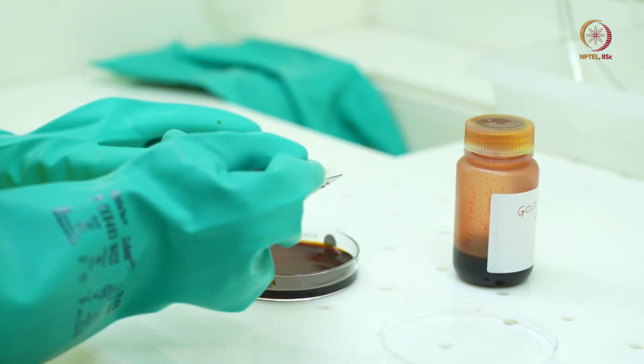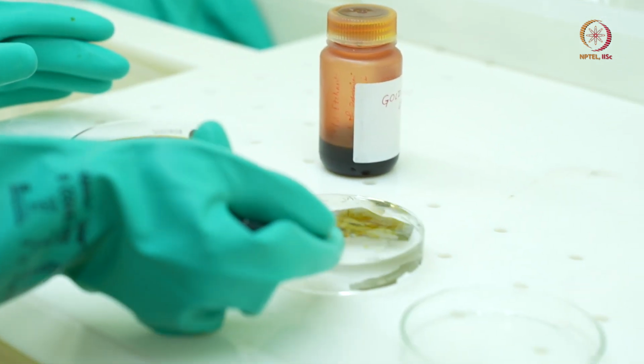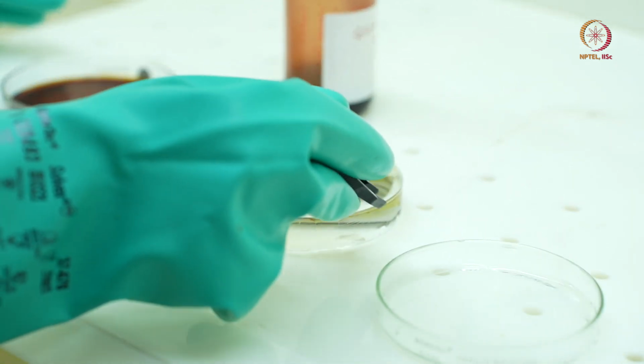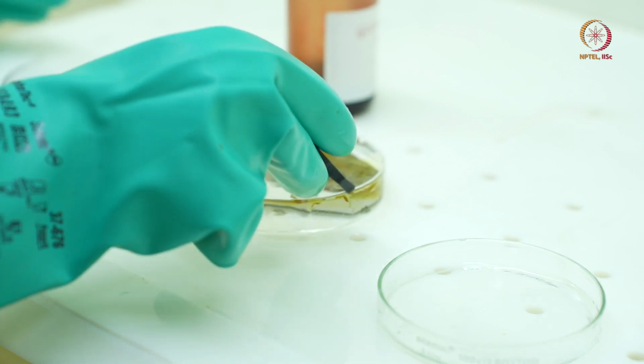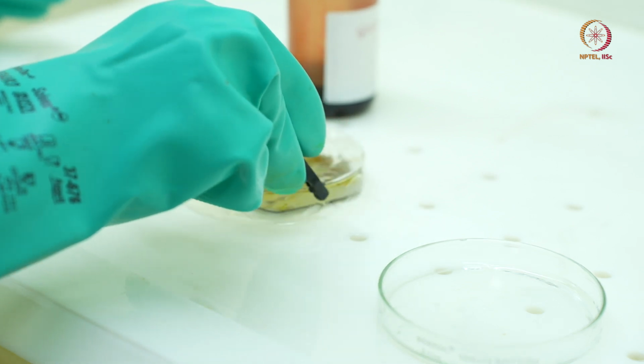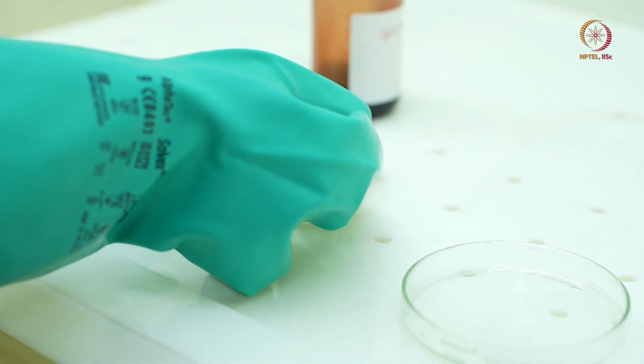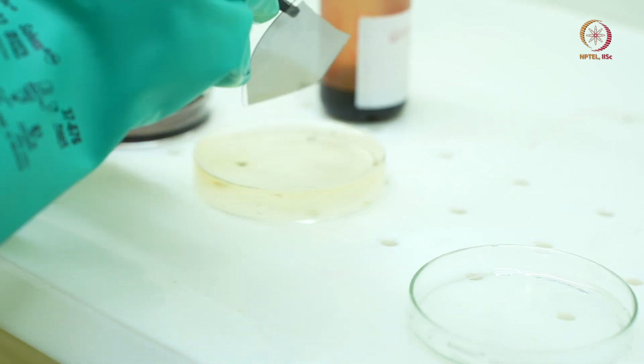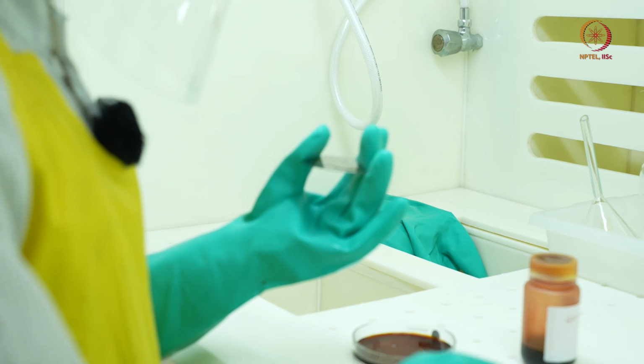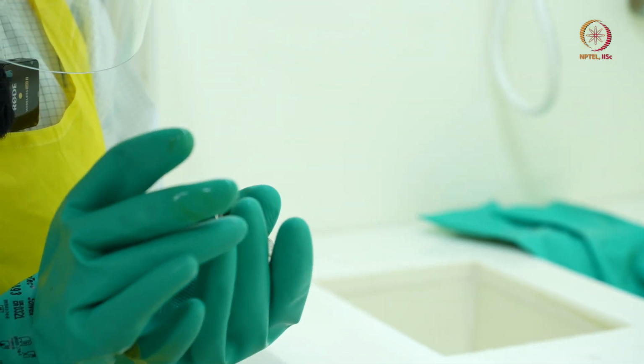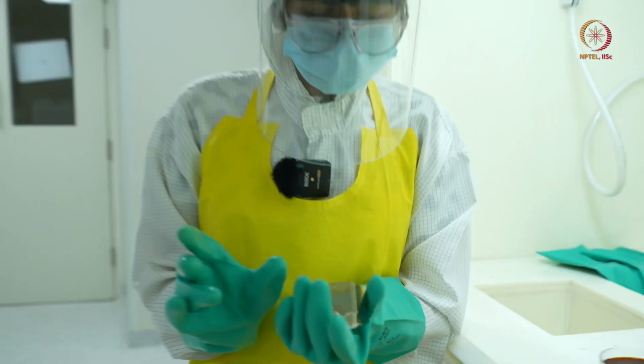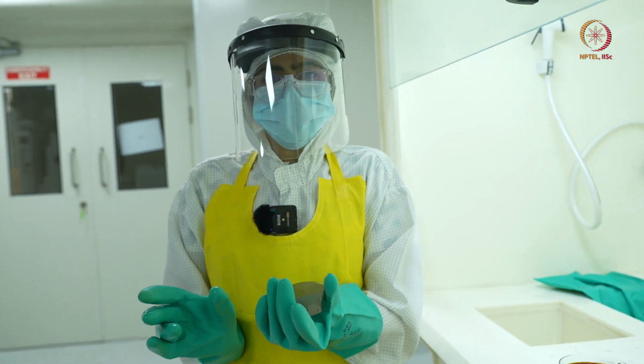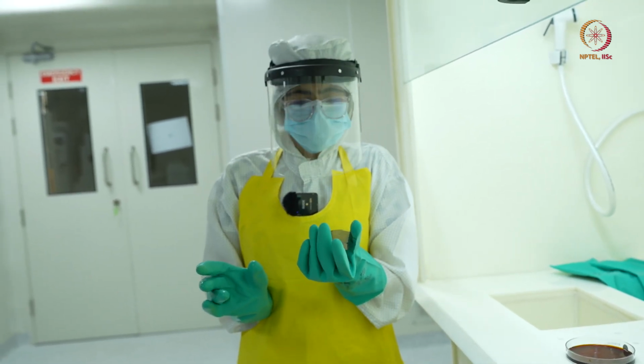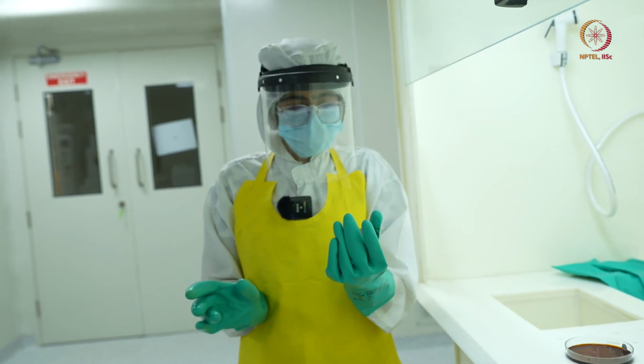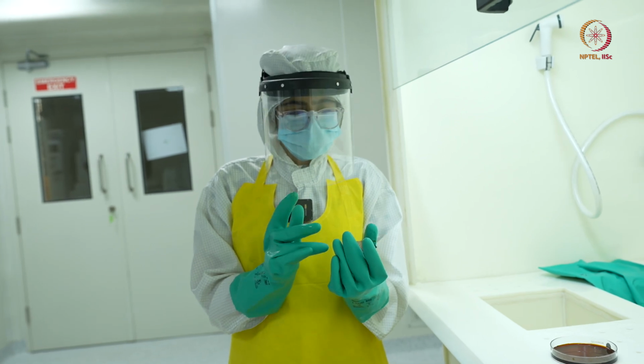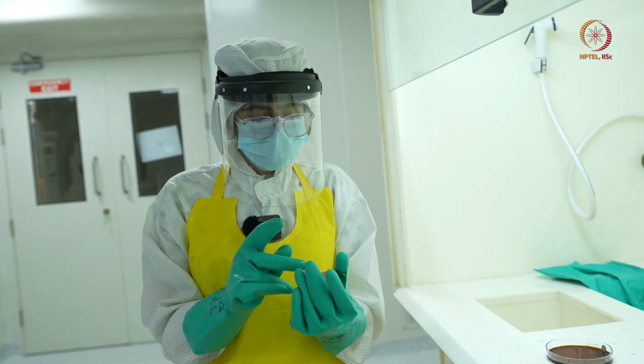Now we'll put the sample in DI water so that the gold etchant will wash out. So I'm putting in the DI water. This petri dish I have already filled with DI water, and I'll just agitate. I'll just clean this. So as you can see, the sample which was yellowish in color because of gold, now it has turned silverish because we have coated titanium onto it for the adhesion of gold with respect to the glass wafer. Now to remove this DI water, I'll use the blow dry nitrogen gun to make it dry.